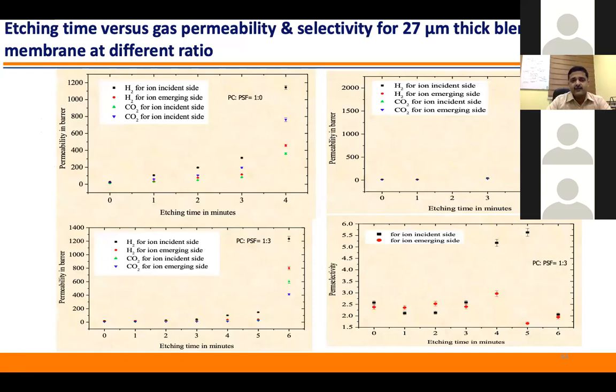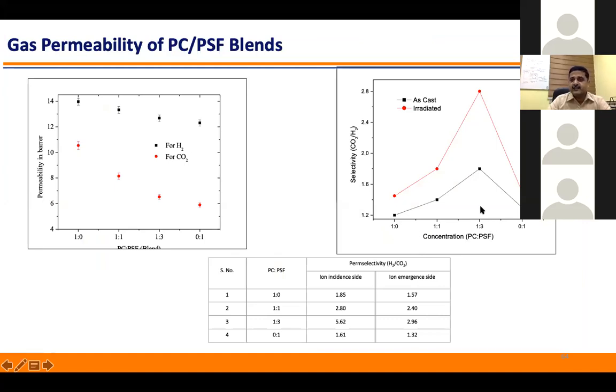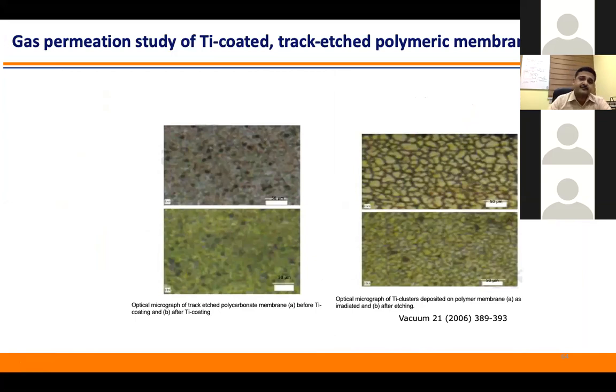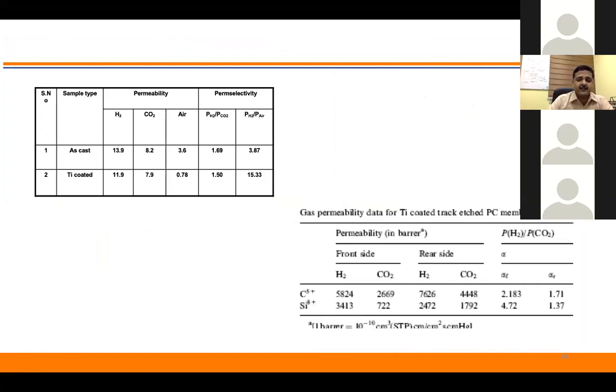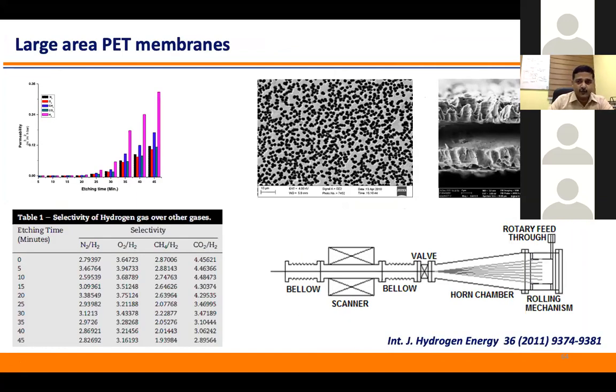And it is true for other membranes also. We have tried making them as blends. So this is polycarbonate polysulfone, in different ratios, but you see here it is higher for the 1:3 ratio, ion incidence side from 5.6, ion emergence 2.9, because this is an asymmetric membrane. We tried coating them with metal. So this is the titanium coated membrane. Most of the pores were covered when we did the coating, and the gas permeability is very poor.